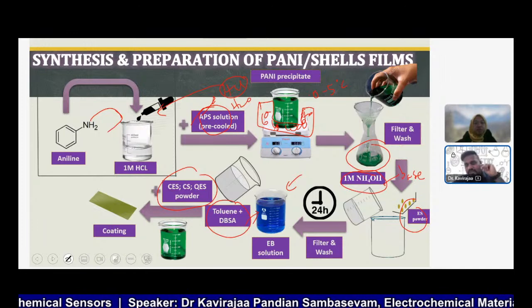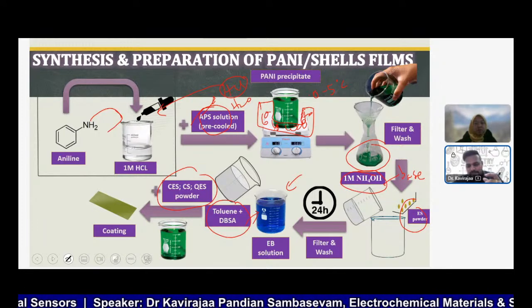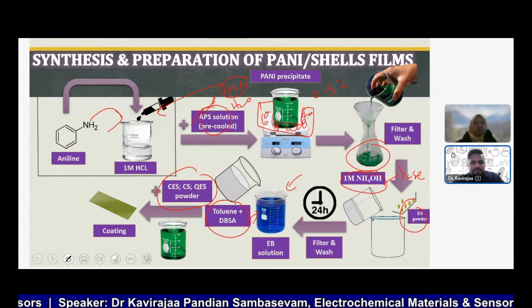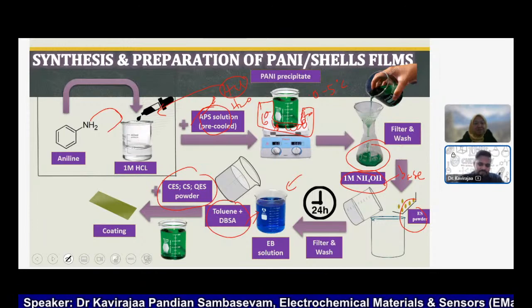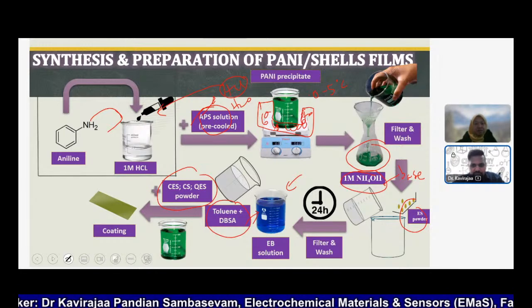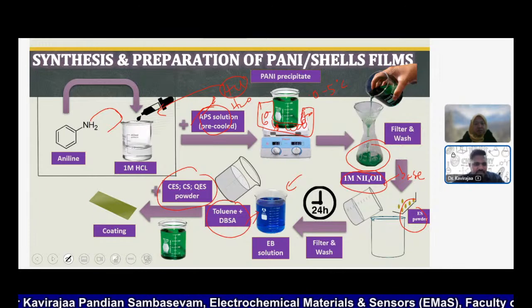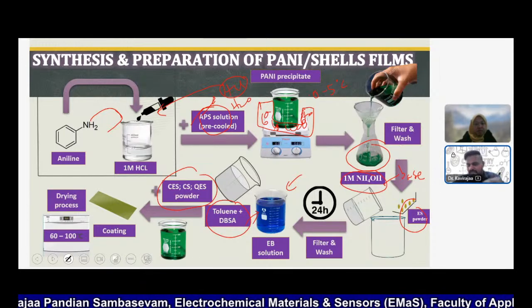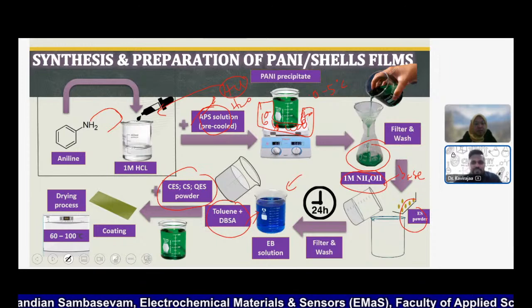We normally use a microscope glass slide, because glass slide is cheap. Initially it's not conductive. Once we have coated it with this conducting polyaniline, it will be conductive. And then we will dry the film, and then we can use it for the sensor measurement.